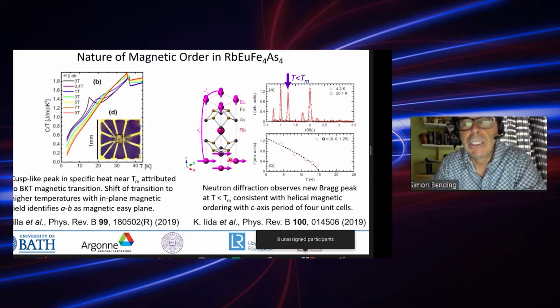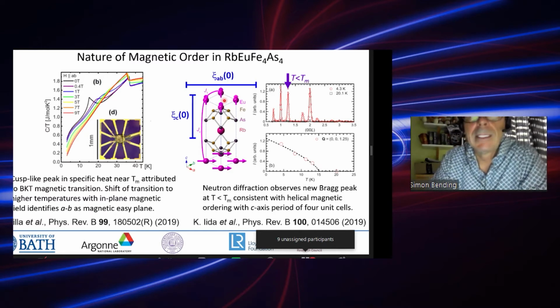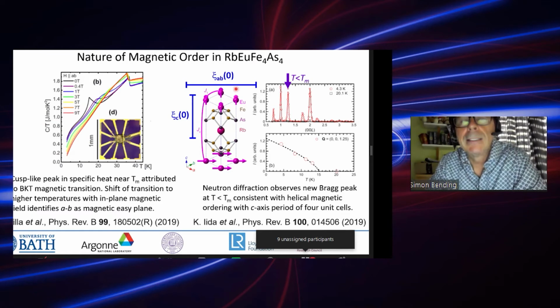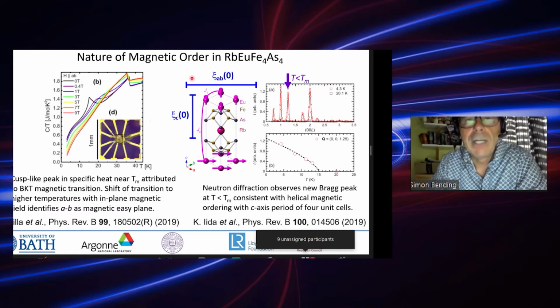So in this sketch here, which is just 1 unit cell, you can see that the moments have rotated from being along the x-axis here to being in the plane here. They've rotated 90 degrees, or perpendicular, into the plane here. What's interesting, though, is to superimpose on this the zero temperature coherence lengths. So here's the AB coherence length. That's perhaps not so important, but the interesting one is this c-axis coherence length.